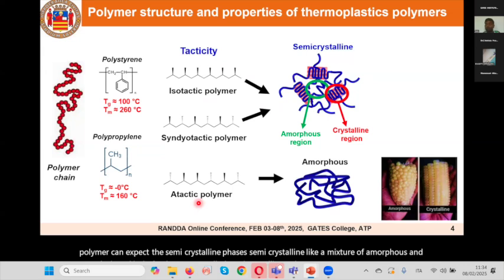Whereas if you take the atactic polymer, the phenyl groups are randomly arranged in the polymer backbone. Due to the randomness of the arrangement of the phenyl groups, this polymer cannot exhibit semi-crystallinity. This system is always amorphous only. So now we understand the effect of the phenyl group arrangement on the physical properties. If the polymer chain has a regular arrangement along the backbone, it can exhibit semi-crystallinity. If it is random, it remains amorphous only. The difference between amorphous and crystalline can be understood by looking at this photograph. Okay, coming to the difference in the semi-crystalline polymer.